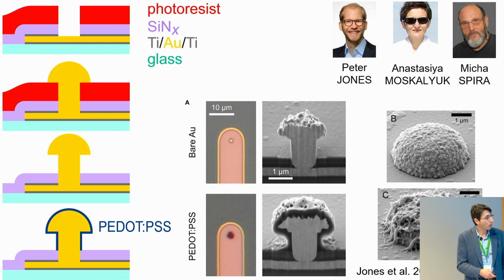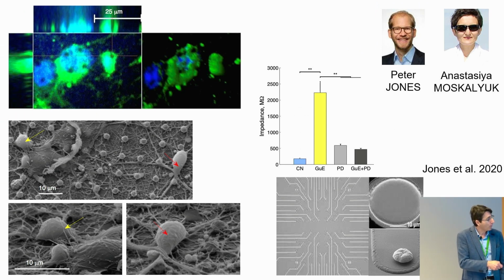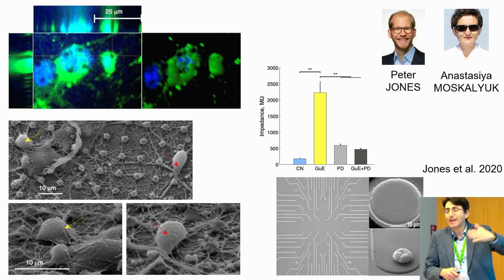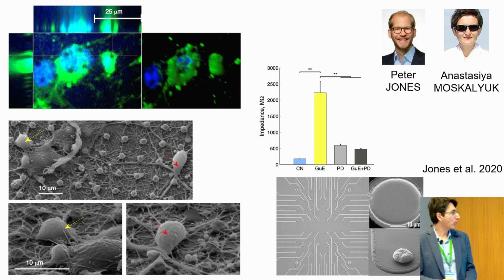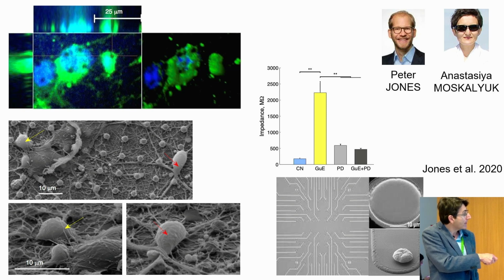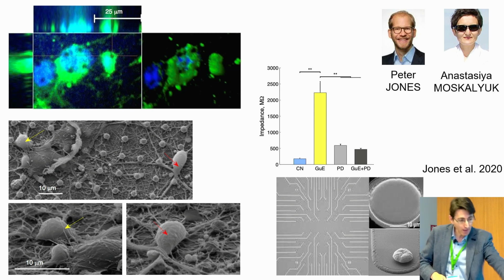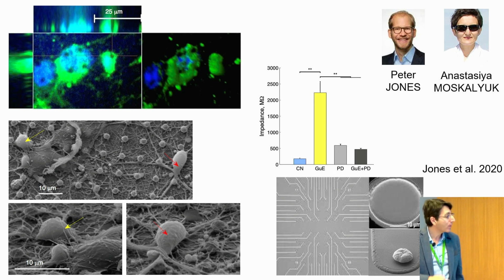And this indeed worked. Just very briefly, I'm showing a confocal imaging where you see in black these mushrooms and in green the cell. If you use this stack of confocal images, although it's not as conclusive as electron microscopy, at least it is live, it doesn't require fixing the tissue, you see that from either side, it seems that there is a tight contact between the membranes and the engulfed microelectrodes. You see here a little bit from the scanning electron microscope in which it seems in one case that really neurons, dendrites and neurites are hugging, or the soma itself is apparently hugging the electrodes.